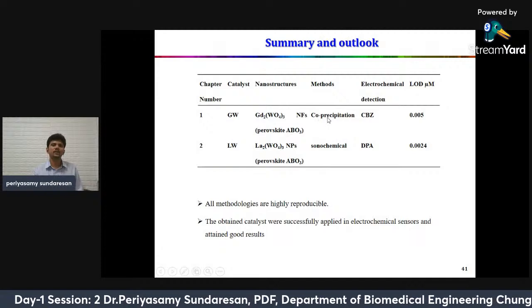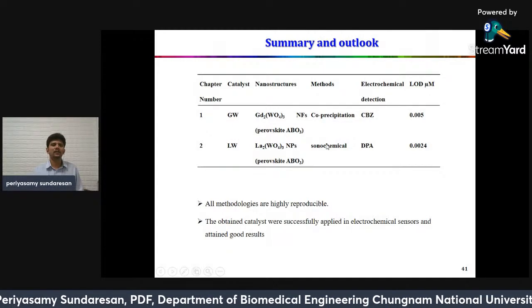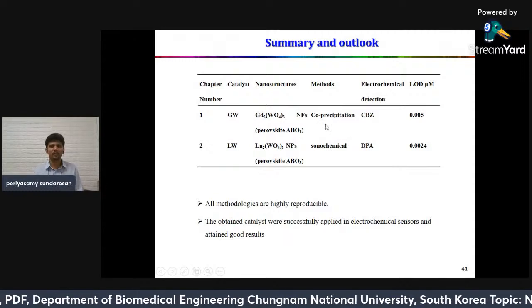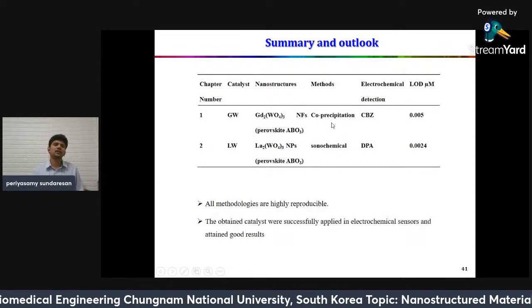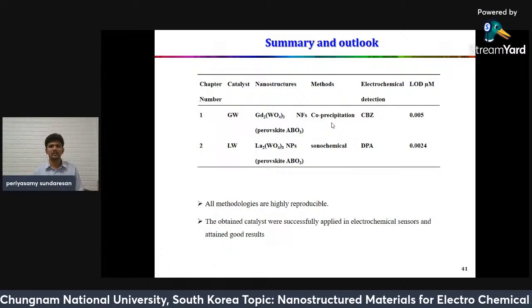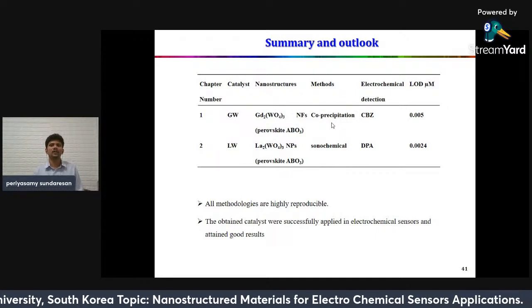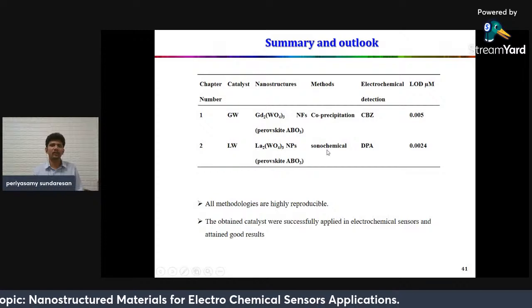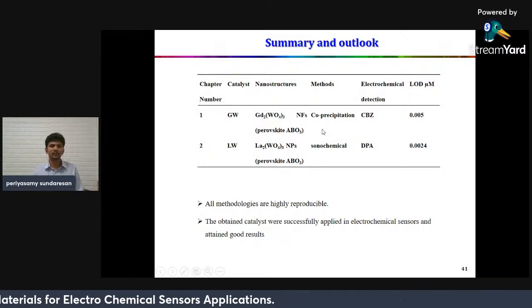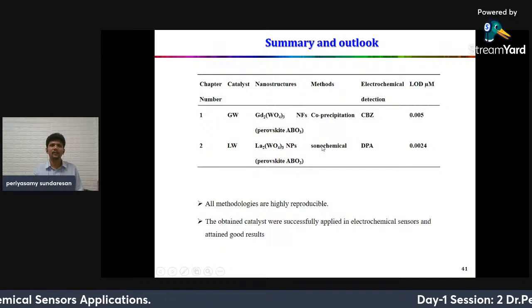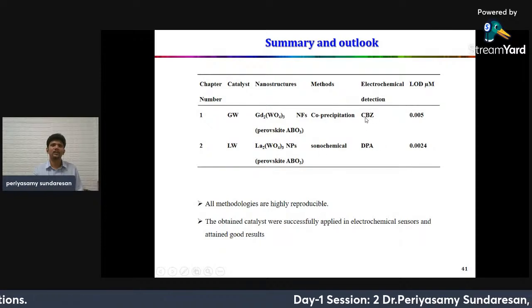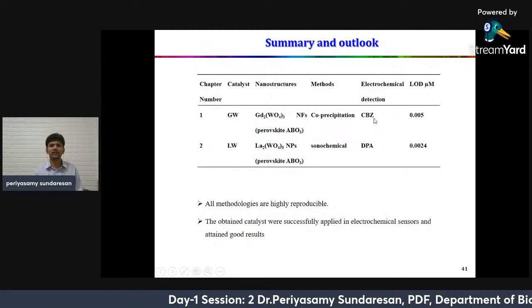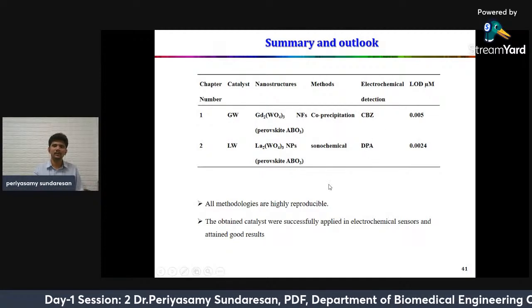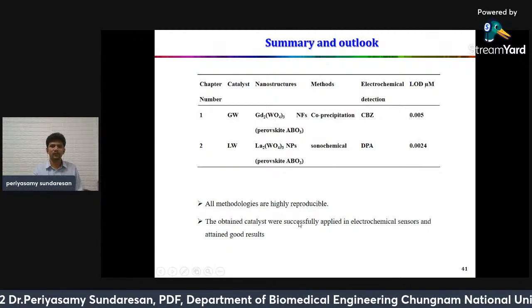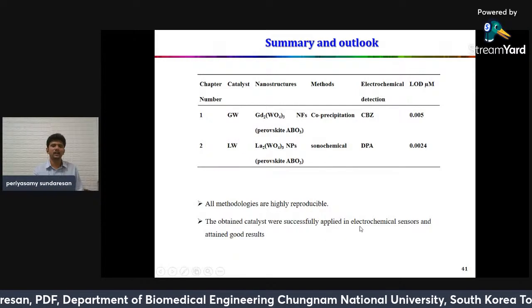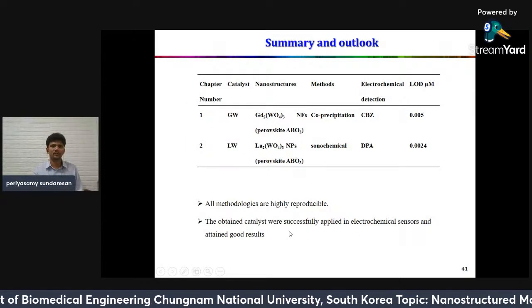Both materials were prepared with simple synthesis methods like the sonochemical method and the co-precipitation method. Both methods don't need any special instrument, and they are time-saving methods for the synthesis procedure. This synthesized material was applied for electrochemical sensor studies for carbendazim and diphenylamine. This method is highly reproducible, and the electrochemical sensor successfully attained good results.